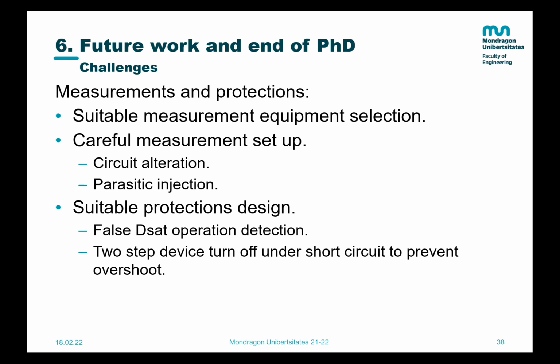You also have to consider that if there's actually a short circuit in your module and you turn it off too fast, you might provoke over voltage in the device and destroy the device, not from the short circuit, but from the over voltage. So there are drivers that have this two-step turn off already programmed in there, and they turn off the SiC devices slowly in order to control that overshoot. So these are things that designers need to consider when switching from silicon to silicon carbide.